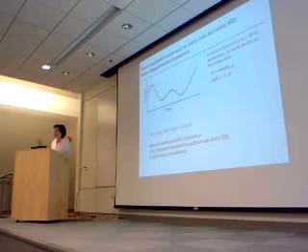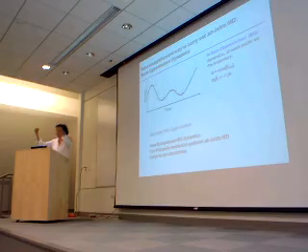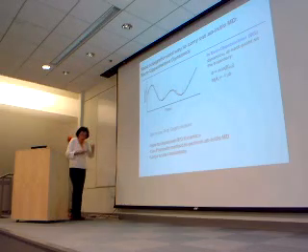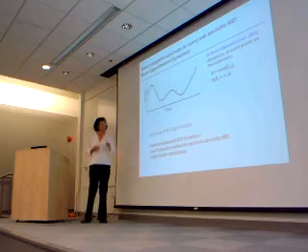This is really the most straightforward way of doing first-order molecular dynamics. You start from ionic positions, do a DFT calculation, apply the Hellmann-Feynman theorem, get forces, move the atoms, and repeat the procedure again to get your electrons and your forces and sample your potential energy surface. It is not as trivial as I make it sound right now.